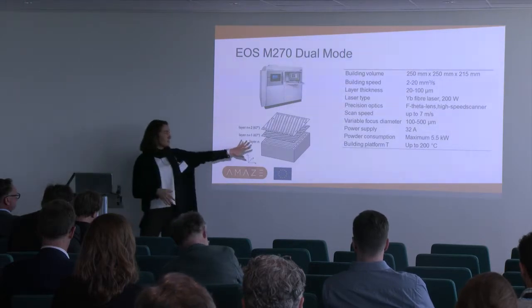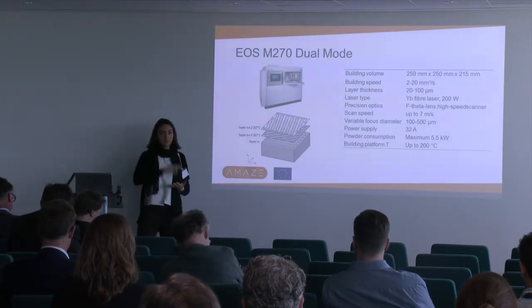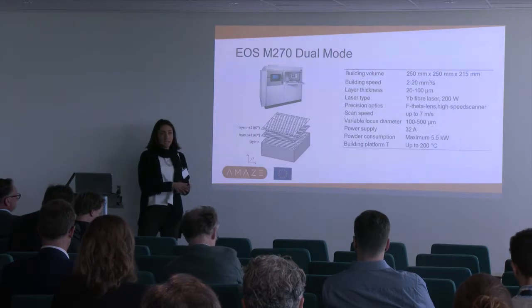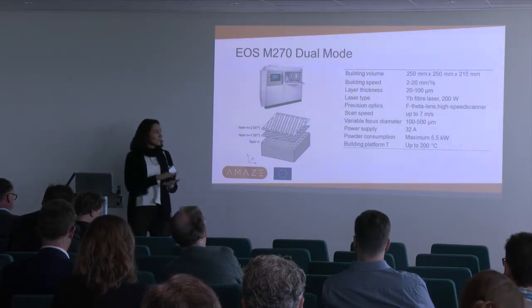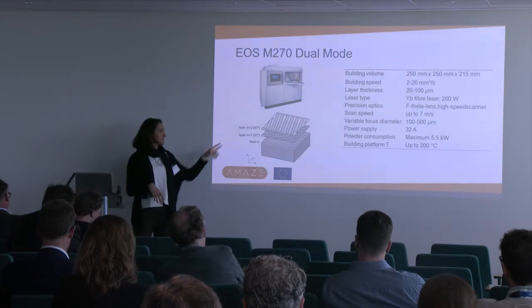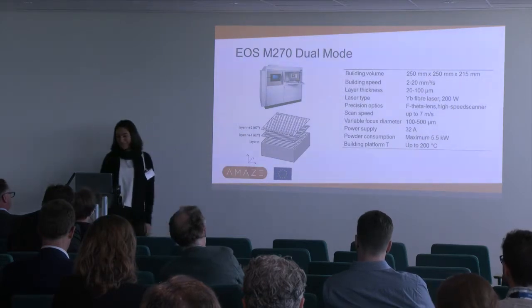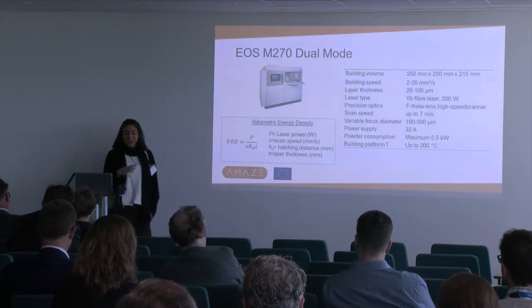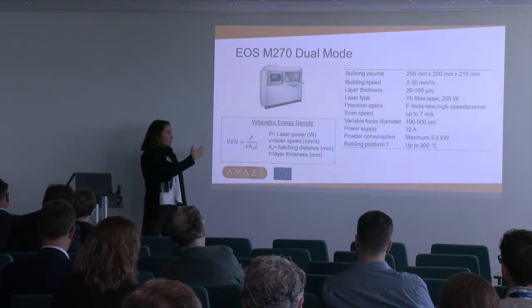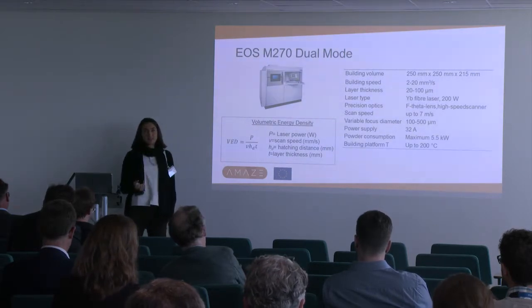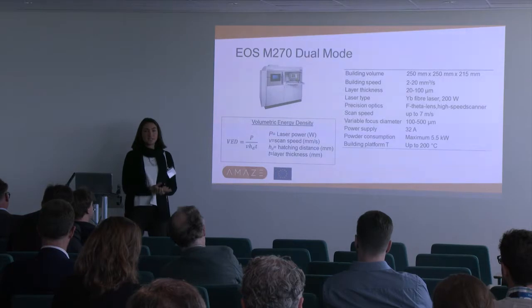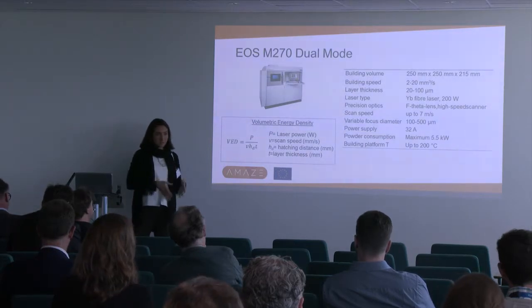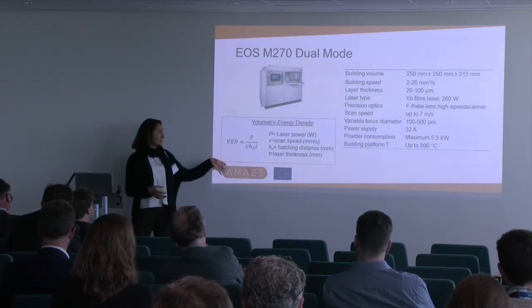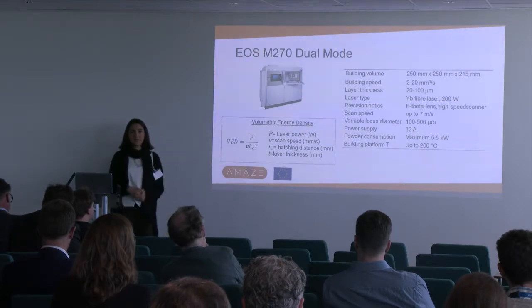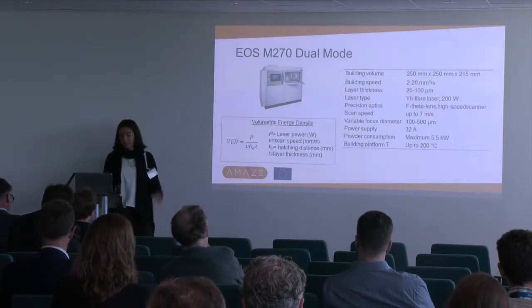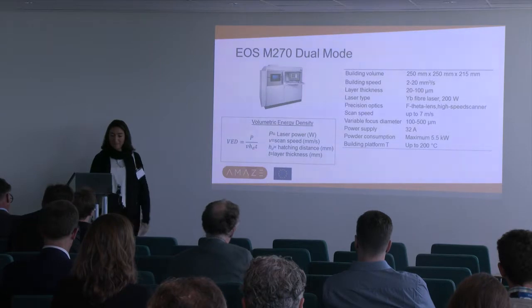This is the scanning strategy we use. So we have some scans, and then every layer the scan direction rotates by 67 degrees. In most of the presentation, we will use the volumetric energy density. It's a parameter that gives an idea of the energy input that we give to a scan. So it's power divided by scan speed and some other parameters. And it can only give an idea of what's going on.